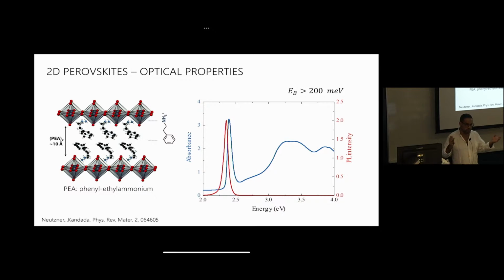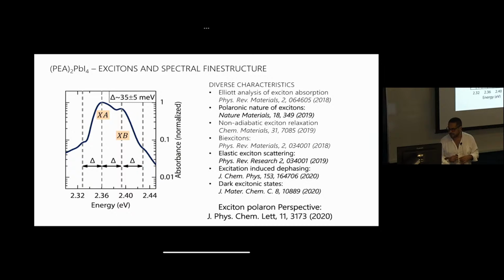Here is the absorption spectrum over a rather large spectral range. At room temperature, you see your nice exciton resonance. You cool it, here at I believe 30 Kelvin, and you see some spectral structure. You don't have one peak; when I plot this on a log scale, you have at least 4 peaks. This is not a new observation. It has been reported since the 1990s, when the previous incarnation of this field was very much interested in these materials. That spectral structure seems to be quite universal, quite general in these materials.